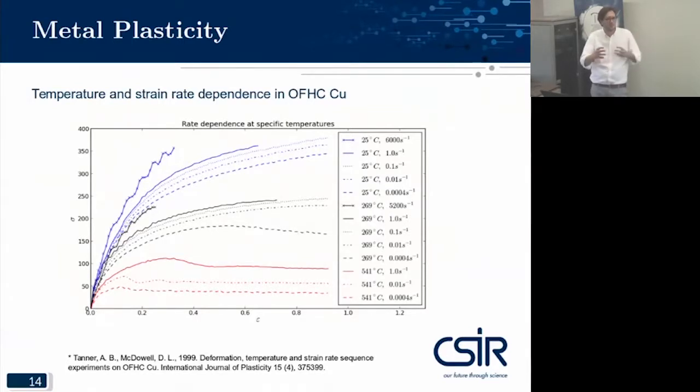And there's a lot of thermal diffusion and interactions between the molecules. So dislocations can start to diffuse as well as recrystallize. Grains start reforming and new virgin material is created in locations where you had a very high concentration of dislocations. So really, materials deform pretty complexly in terms of temperatures and rates. It's not just a simple statement of how a material deforms plastically. This is a fairly commercially pure copper.